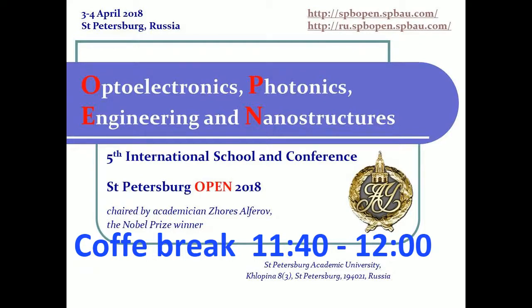But one has to say that excitons were not discovered in gallium arsenide, but in cuprous oxide, and this lasted roughly 20 years since the first proposal by Frenkel, by Yevgeny Gross, also at the Joffe Institute, and I want to point out that he used artificial crystals, and this was his absorption measurement performed at 1.3 K, and you see here the n equals 2 exciton, 3, 4, 5, 6, 7, 8. So he pretty much discovered already the hydrogen-like exciton series.